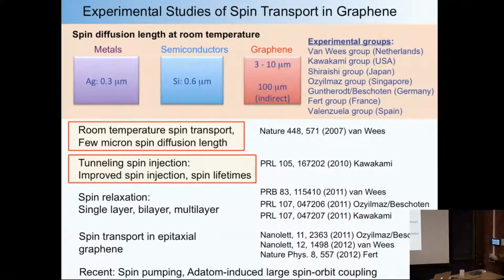And I want to highlight there's been quite a lot of advances since 2007 when this field really took off. And so this work by Van Wees showed that you can have room temperature spin transport and a few micron spin diffusion length. And he also saw spin precession, which really proved that it was indeed a spin signal as opposed to some artifact. And I think the next really important advance was the development of tunnel barriers for spin injection. So this, and I'll tell you about this in this talk, this really improved the spin injection efficiencies, and more importantly, it improved the spin lifetimes. There was a big mystery, which I'll tell you about, in terms of spin lifetimes. They're way too short. And we're trying to understand, well, what causes them to be too short?